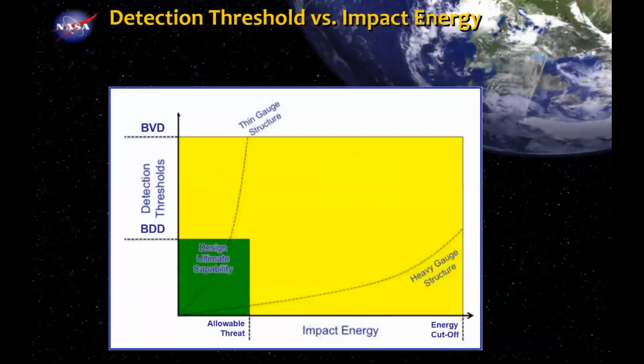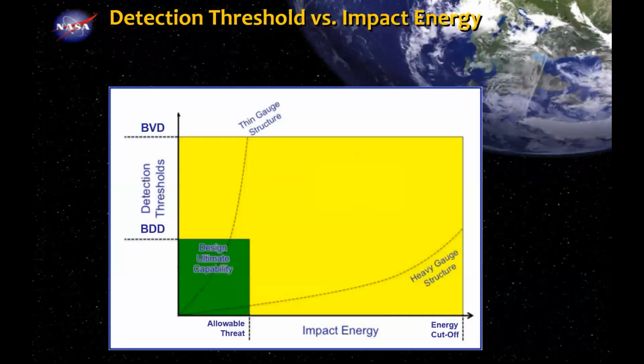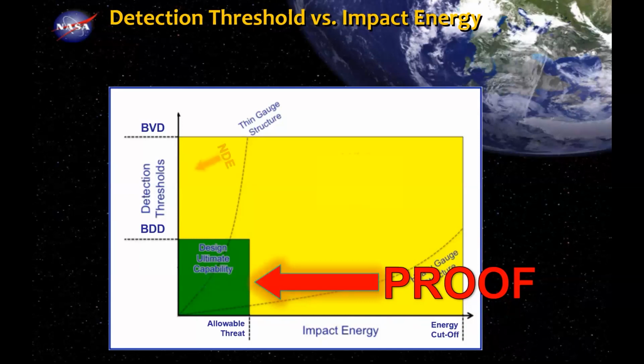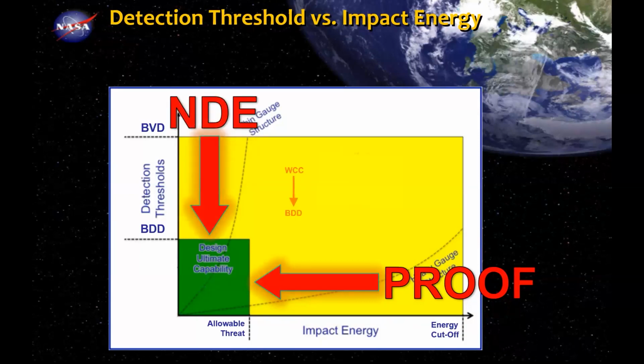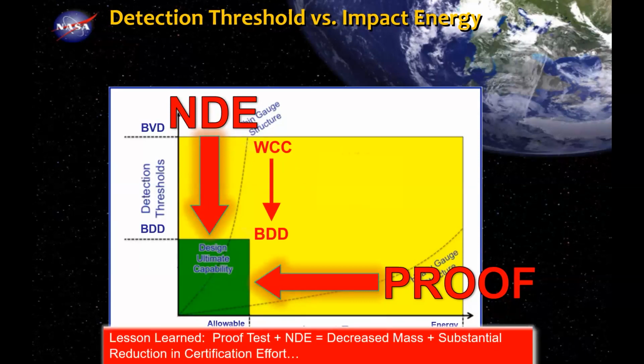But if every flight we were able to do something like an NDE inspection, we can push that space. That's okay. You can go to the next one because I'm illustrating it on the next one, and this will be the last slide. So if we think about our damage all the way to the yellow box, and the amount of impact energy there, it's huge. Same thing with the barely visible damage. And I just showed you that you might have 100 foot-pounds of damage before you can see it. So you have to design to a huge, huge threat envelope.